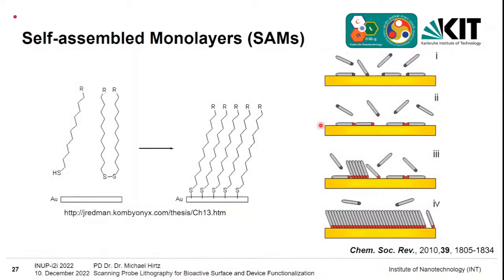On this, I will shortly talk about what a self-assembled monolayer is. I already mentioned this once. It's basically a self-organization of, most of the time, linear molecules. One very famous system for this is a thiol system. So you have a thiol and a hydrocarbon chain. It can have different chemical functionalization at the end, and when you bring it near a gold surface, they will attach to the surface over the sulfur here. And you will end up with a kind of, let's say, molecular crystal that grows in 2D on the surface. So at some point you will get a very neatly, tightly ordered layer under the right conditions. And by this, you can, of course, change the surface chemistry to almost arbitrary things when you change the functional moiety at the end.